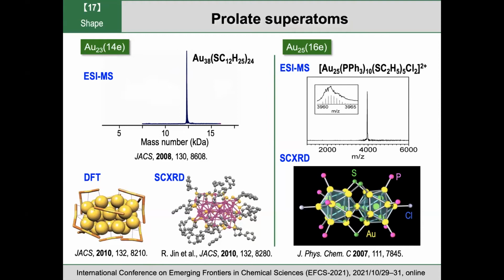And this one is another example. Gold-25 clusters protected by 3 types of ligands. Of course you can ignore the ligands. You can see 2 icosahedra sharing a single atom. So the number of core atoms is 25. This is a single crystal structure. This type of structure can be viewed as a quasi-molecule made of superatomic gold-13 superatoms.